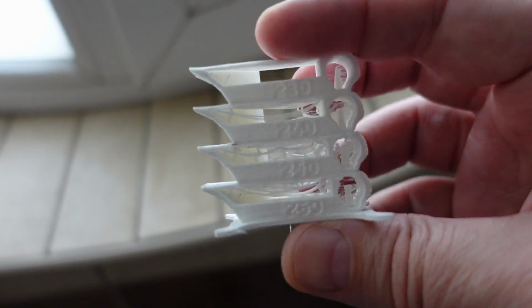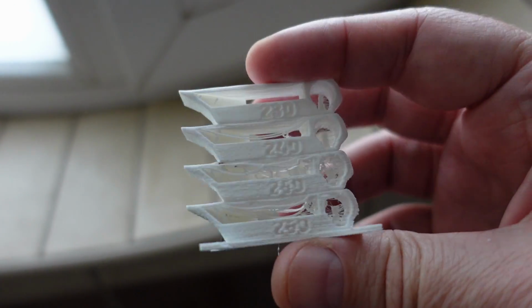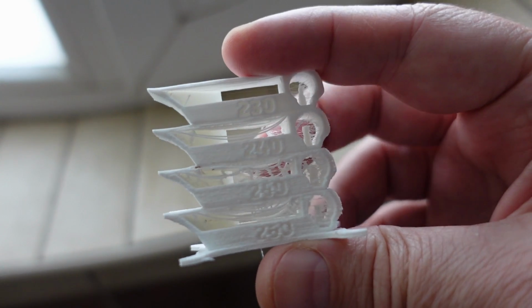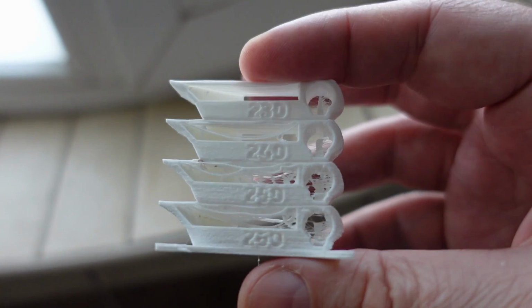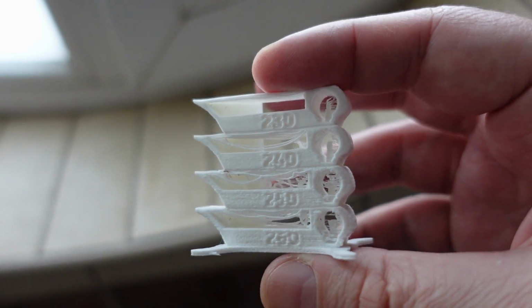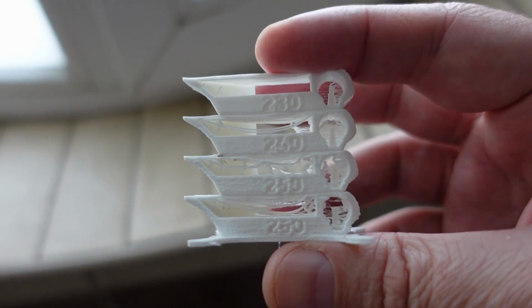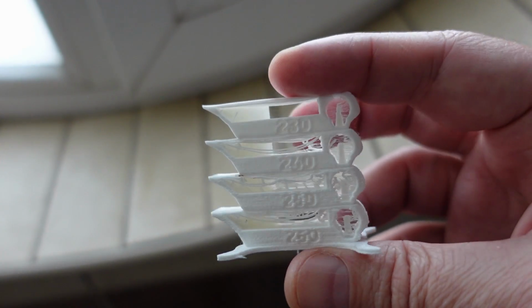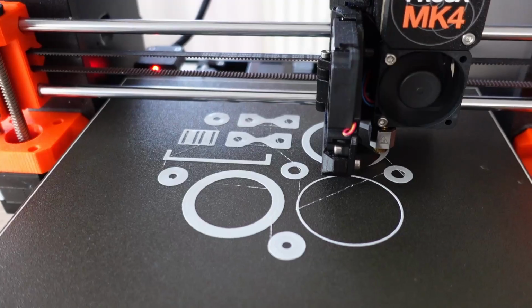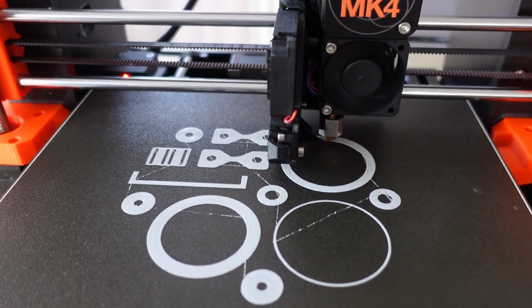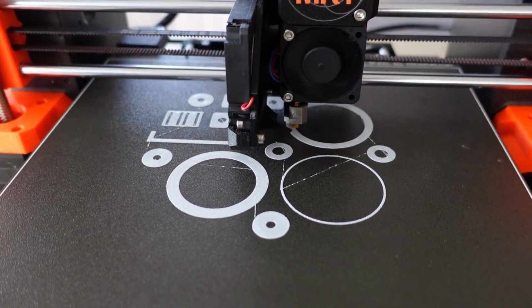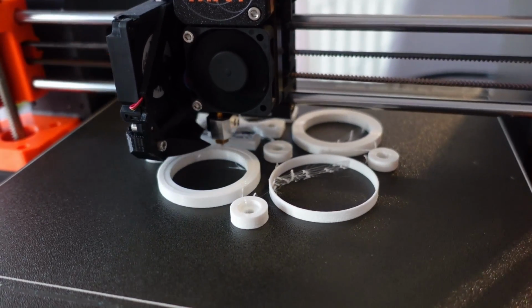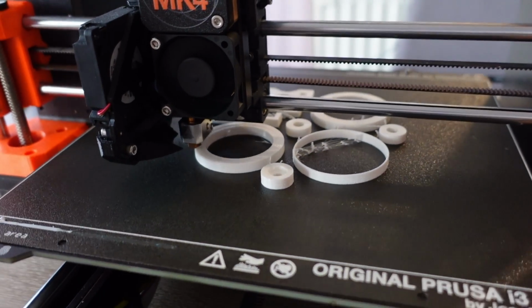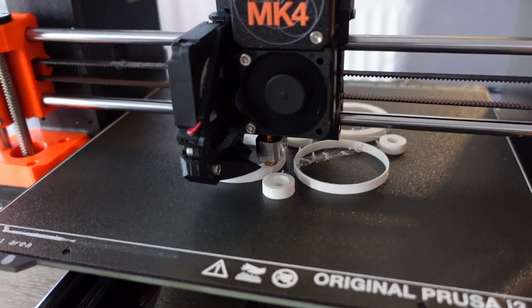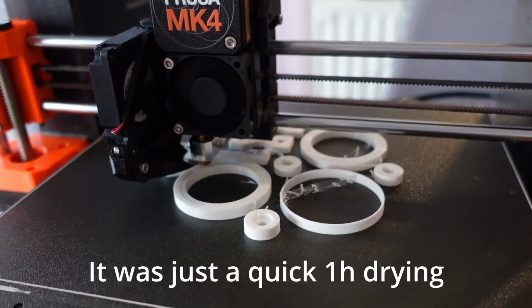Taking a closer look at this temperature tower, the overhang is okay. I think not the stringing but the bridging is the biggest problem here, but it depends a lot on the settings. And I think with just minimal drying I can print everything at 250 degrees Celsius. Great first layer, but I can see that I will have a few strings between the objects. The printing is at 65% and I think this amount of stringing is acceptable, but definitely if I dried it more it would be better.